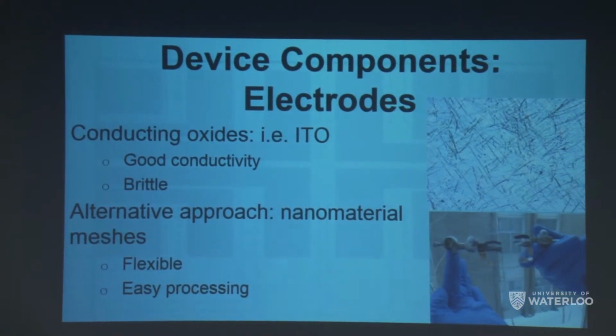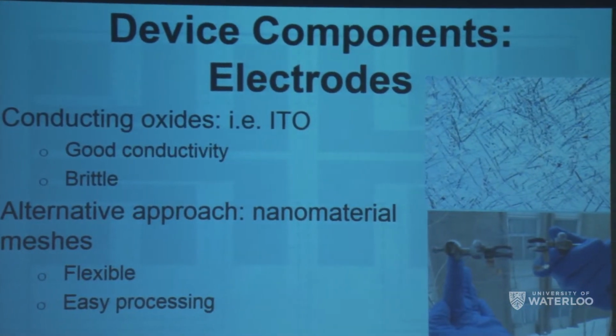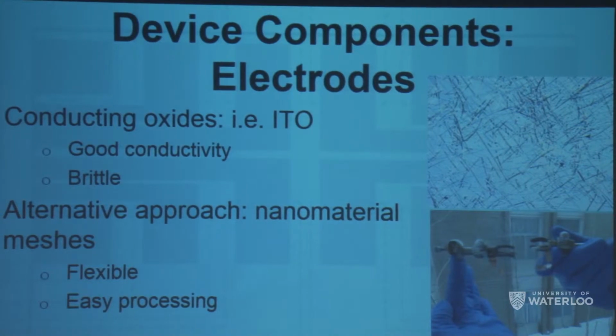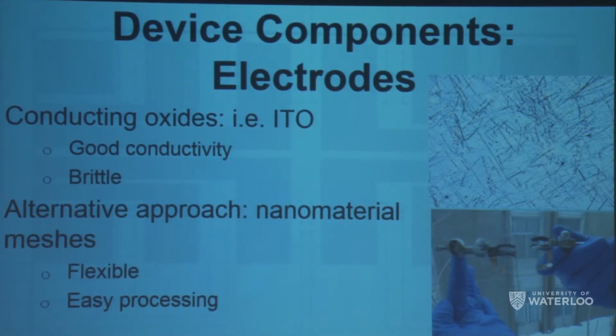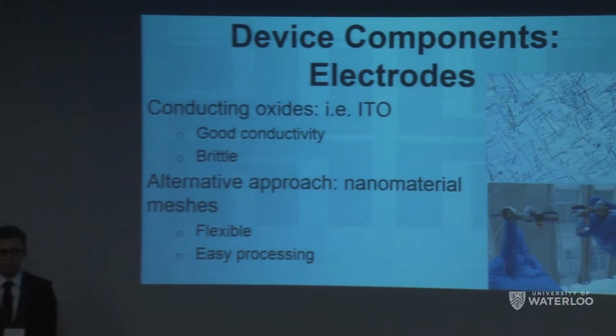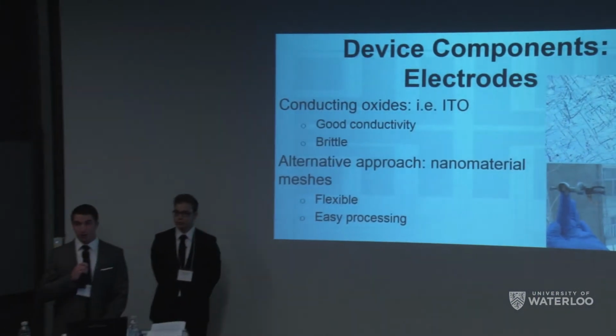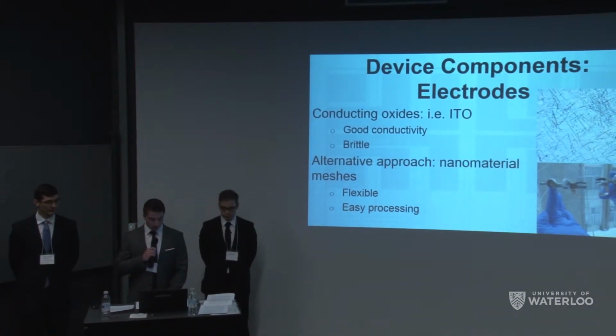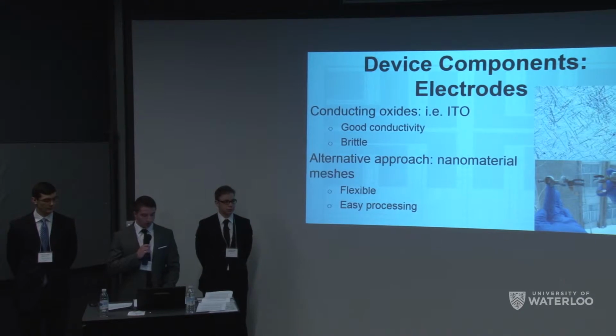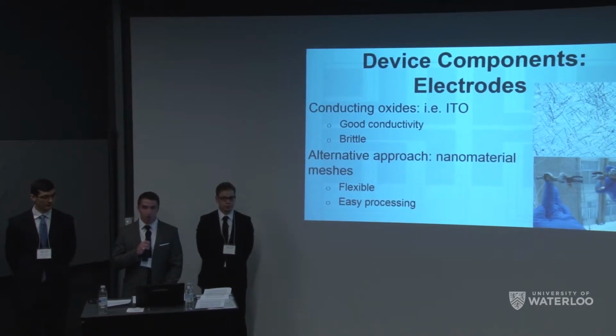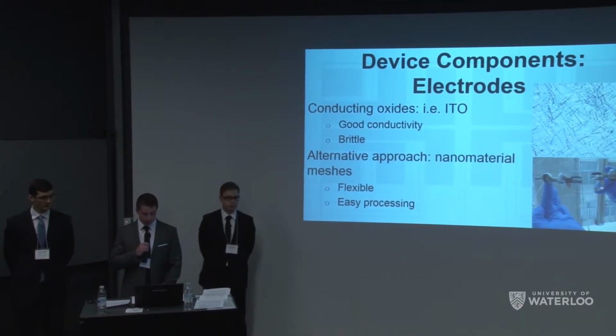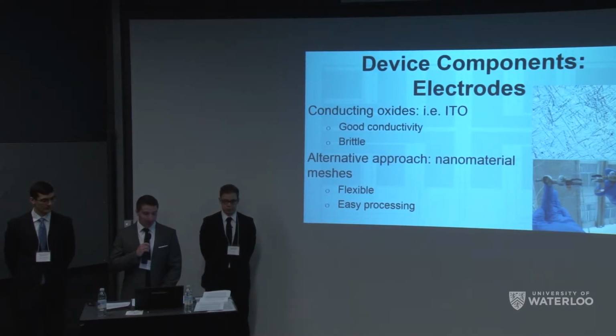Unfortunately, these and the other conductive metal oxides tend to be very brittle and therefore inflexible, which prevents lamination as a scale-up process. We decided to circumvent this problem in the nano way by exploiting size as a physical property. We took conductive silver nanowires with a diameter of 90 nanometers and used them to replace our cathode materials. To put 90 nanometers into perspective, this is about 1,000 times smaller than an individual pixel on an iPhone 6 Retina display.